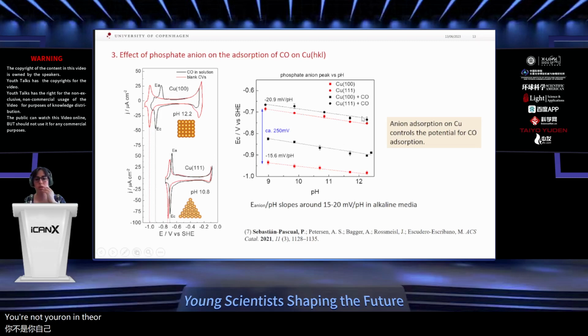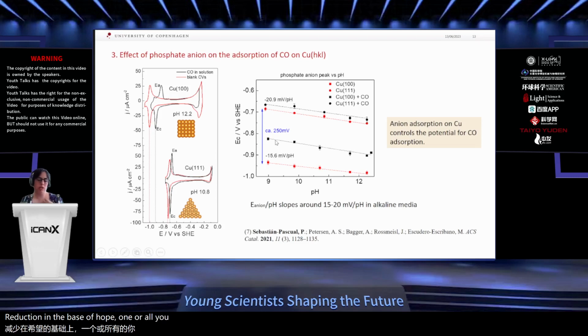So the anion is controlling the adsorption of CO, and it's also controlling the potential at which the CO is going to be adsorbed on copper, which is going to affect also the onset potential for CO reduction. In the case of copper 100, the CO adsorbs a little bit earlier because the CO adsorption seems to be a bit stronger than on copper 111, but it's still controlled by anion desorption. So, all right, the conclusion is that the anion is controlling the adsorption of CO.